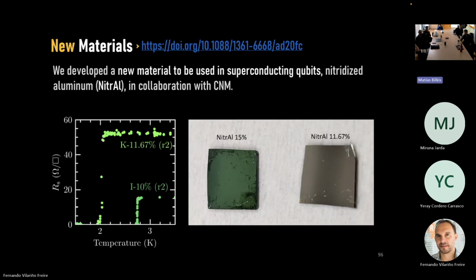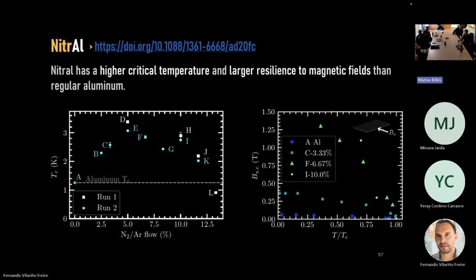We are also invested in developing new materials to be used in superconducting qubits. In this case, we have a paper out where we made the first measurement of thin films made with nitridized aluminum, which is aluminum deposited on silicon in an environment with a lot of nitrogen. Why this? Usually the Tc of aluminum is around 1.2 Kelvin, but these films have a much higher critical temperature, around 2-3 Kelvin, which is advantageous for various applications. Also, they tend to be much more resilient to magnetic fields, which is very relevant in qubit technology for, again, various applications. The hope is that maybe we can replace some parts that we now make with aluminum with nitridized aluminum.